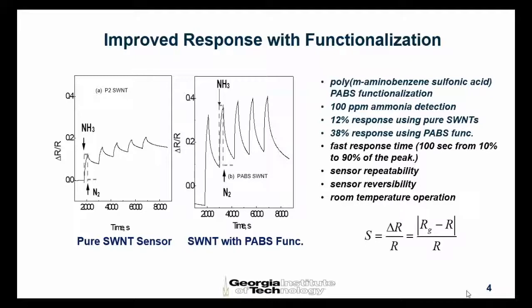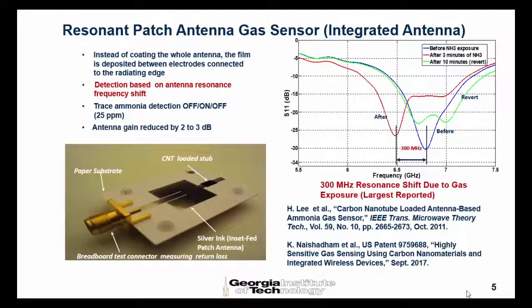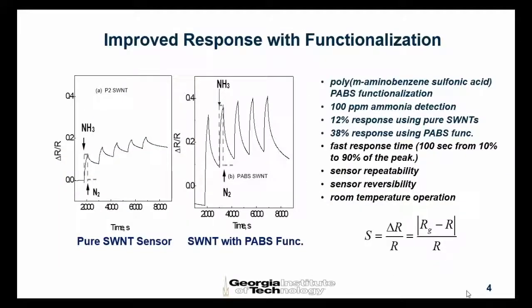And this is our first cut at a nanotube-based sensor for ammonia. This is a simple chemi-resistor, very similar to what I showed you on the previous slide. There are two figures here. One of them is the raw material, which is pure carbon nanotubes. The other one is the raw material functionalized with PABS to detect ammonia. The detection is at 100 parts per million ammonia. Without functionalization, I get only a 12% change in the response, but with functionalization, I get a much higher scale, 38%. The response time is very fast, a few tens of seconds, 100 seconds, and it is repeatable and reversible. When you remove the source of gas, it goes back to the baseline, and it works at room temperature.